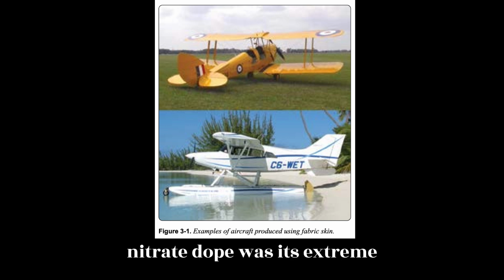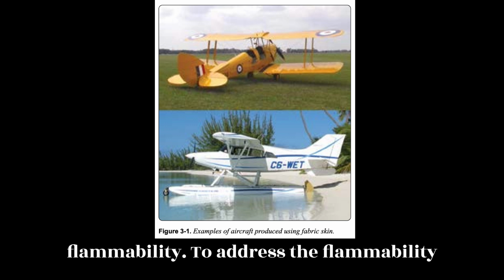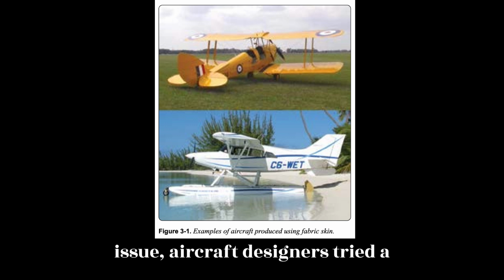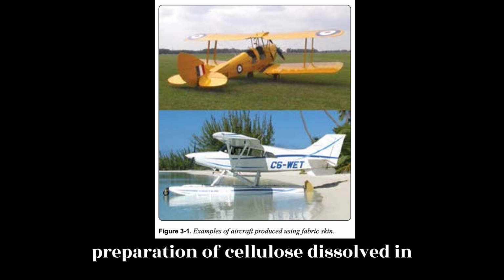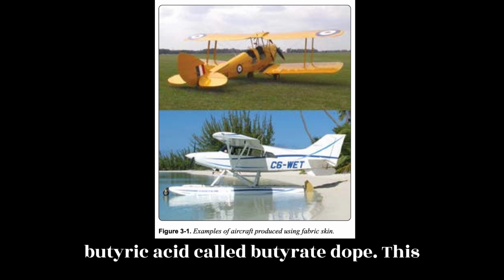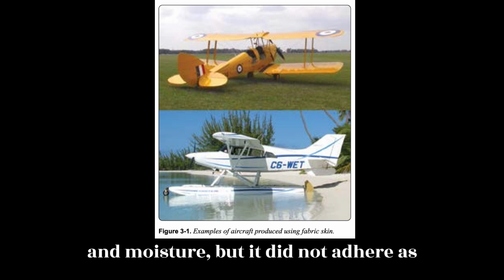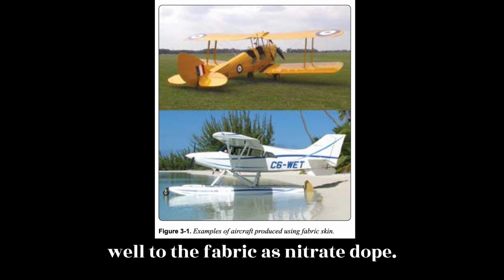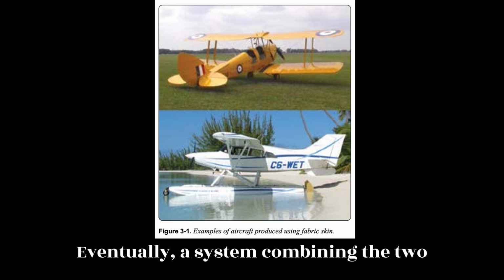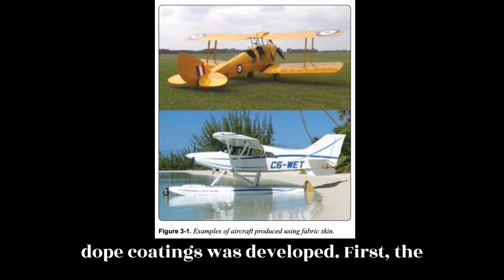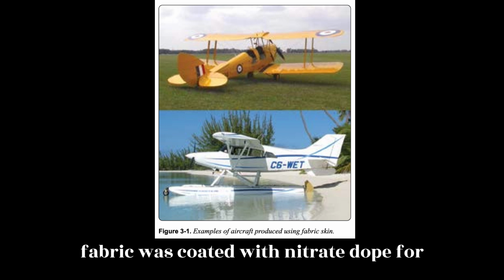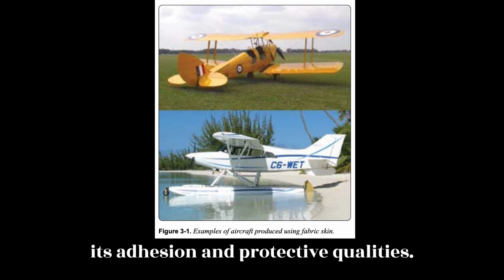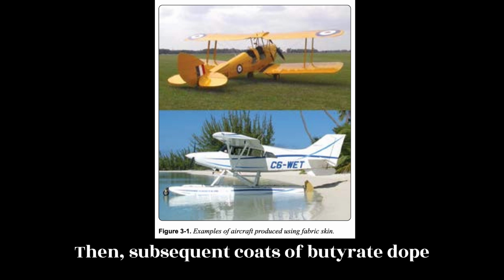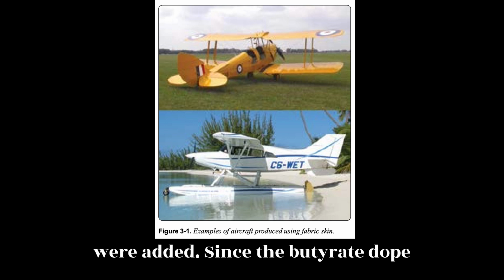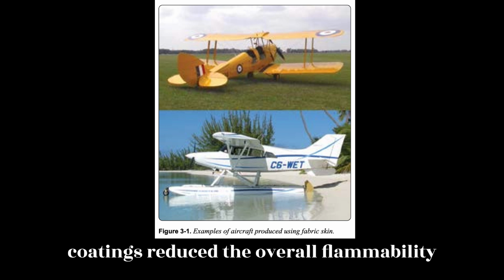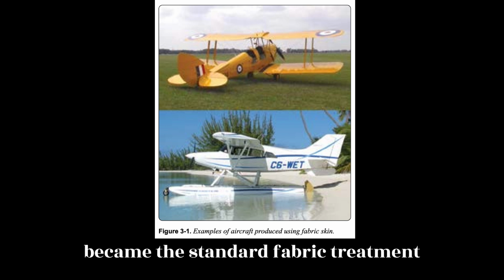The major drawback to nitrate dope was its extreme flammability. To address the flammability issue, aircraft designers tried a preparation of cellulose dissolved in butyric acid called butyrate dope. This mixture protected the fabric from dirt and moisture, but it did not adhere as well to the fabric as nitrate dope. Eventually, a system combining the two dope coatings was developed. First, the fabric was coated with nitrate dope for its adhesion and protective qualities. Then, subsequent coats of butyrate dope were added. Since the butyrate dope coatings reduced the overall flammability of the fabric covering, this system became the standard fabric treatment system.